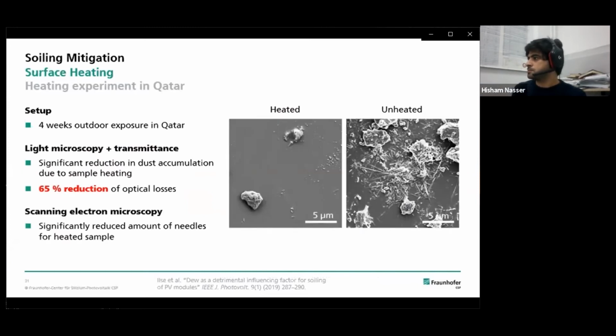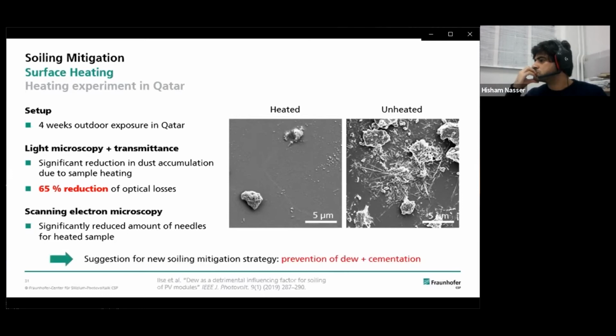Looking at the samples by scanning electron microscopy, a significantly reduced amount of needles was detected for the heated sample. These needles are cementing materials in the region of Qatar, so by heating we strongly reduce the cementing effect. And accordingly, it could be proven that the needles form at the surface during dew events. Because of the high potential of the anti-soiling benefits, the prevention of dew and cementation was suggested by us as a possible new soiling mitigation strategy.